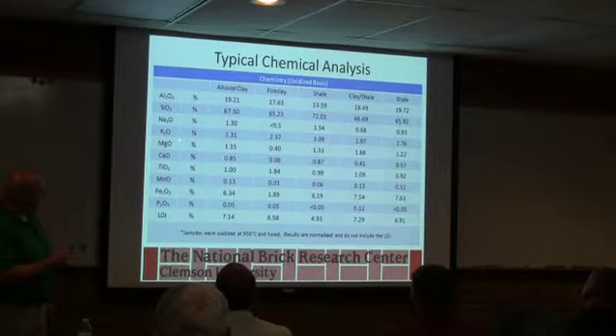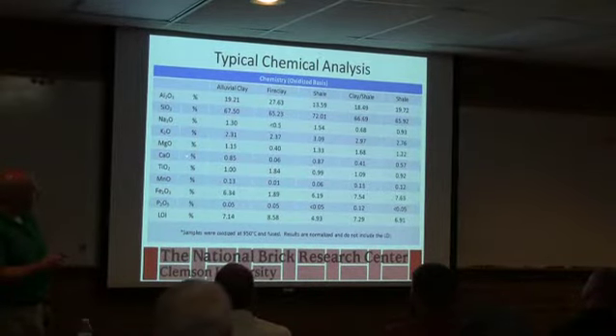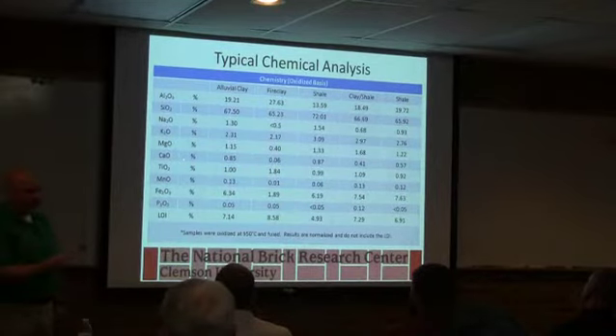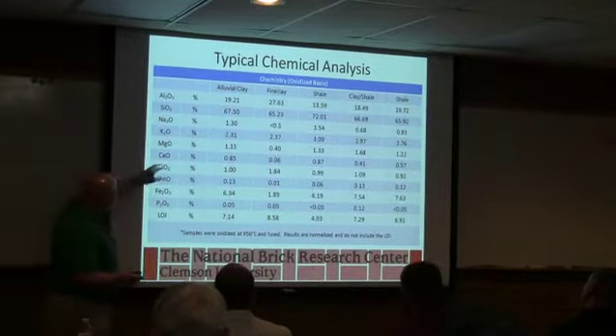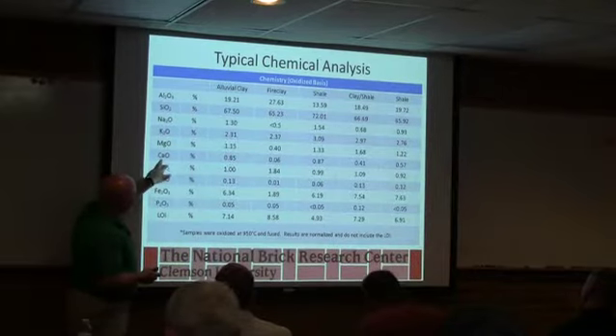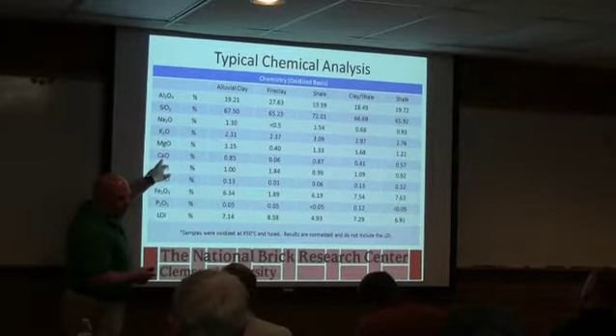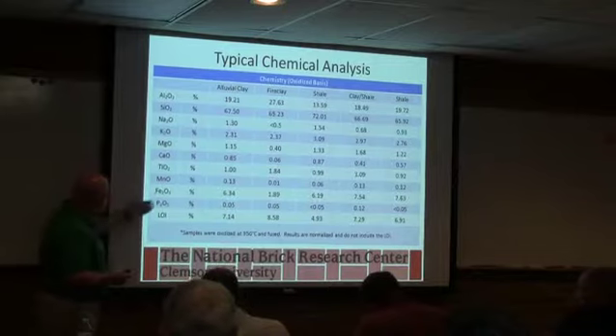To a lesser extent, the magnesium and calcium are also fluxes, but you've got to watch this number. A lot of times, we haven't talked about lime pops yet, but we will. That's a good indicator that lime pops may be a problem, because calcium carbonate is what causes lime pops. So if you see a high number there, that's usually an indication.